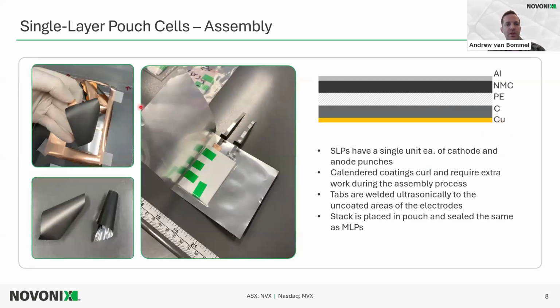So moving on to a full cell, the simplest pouch full cell would be the single layer cell. So I have a side profile here. We have the copper current collector, and on that is coated a graphite electrode. We have aluminum current collector, and on that is coated the NMC electrode. And in between, there's a polyethylene separator. So each of these single layer pouches has a single unit each of the anode that you see here and the cathode that you see here.